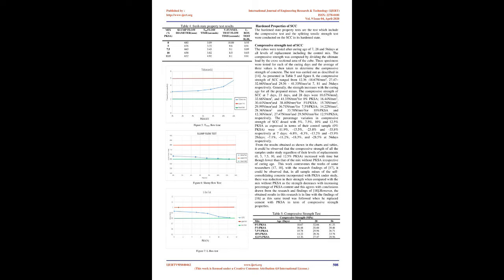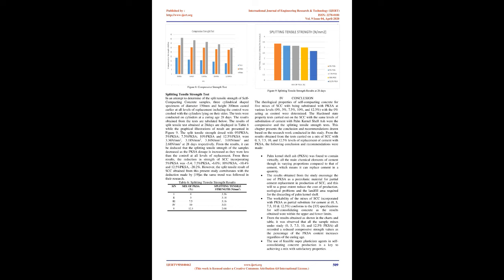The compressive strength of SCC at 7 days, 21 days, and 28 days were 18.67 N/mm², 32.66 N/mm², and 41.33 N/mm² for 0% PKSA, 16.44 N/mm², 30.44 N/mm² and 38.40 N/mm² for 5% PKSA, 15.78 N/mm², 29.99 N/mm² and 36.71 N/mm² for 7.5% PKSA, 14.22 N/mm², 28.36 N/mm² and 33.78 N/mm² for 10% PKSA and 12.36 N/mm², 27.47 N/mm² and 29.56 N/mm² for 12.5% PKSA, respectively.